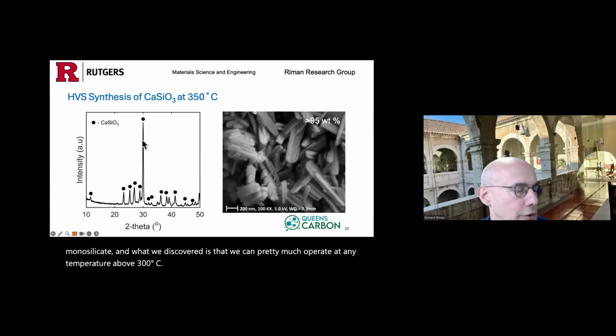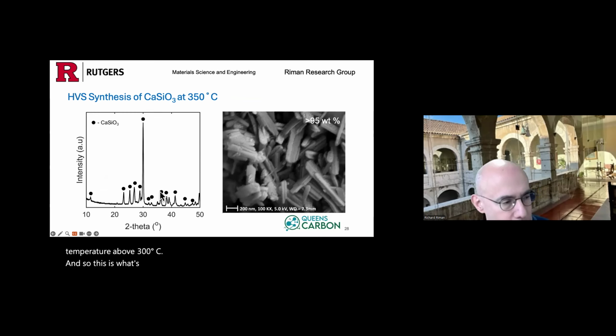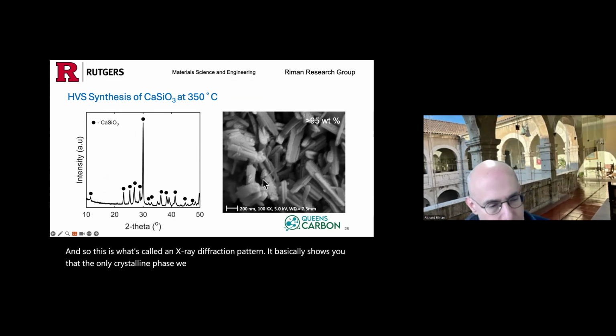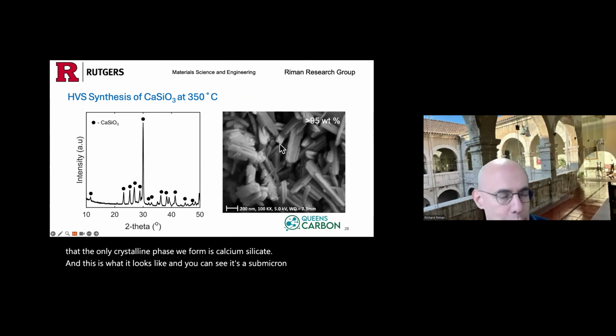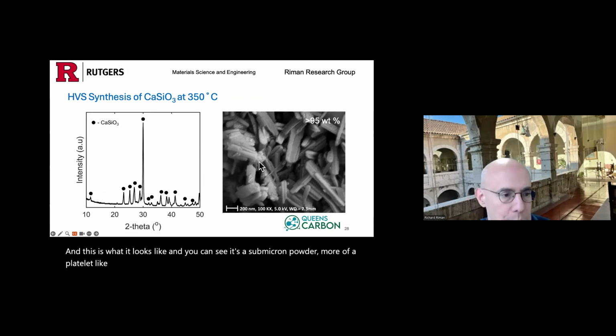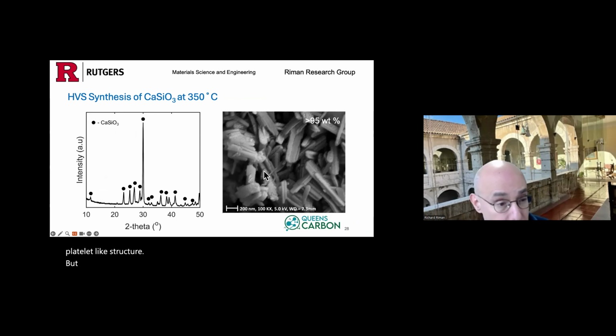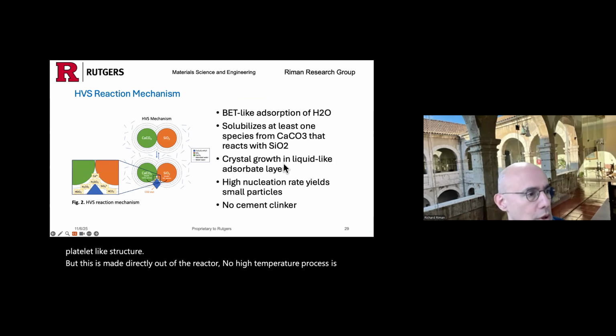And so this is what's called an X-ray diffraction pattern. It basically shows you that the only crystalline phase we form is calcium silicate. And this is what it looks like. And you can see it's a submicron powder, more of a platelet-like structure. But this is made directly out of the reactor. No high temperature process is required.